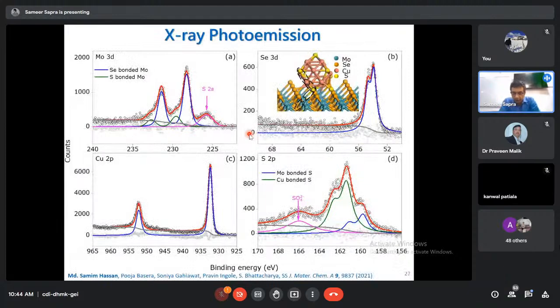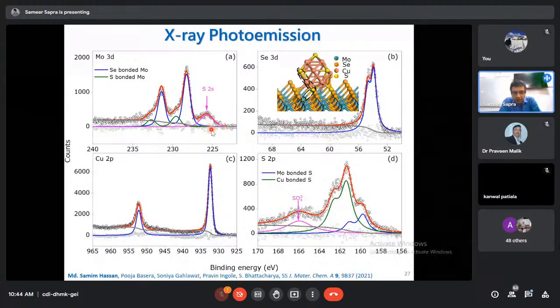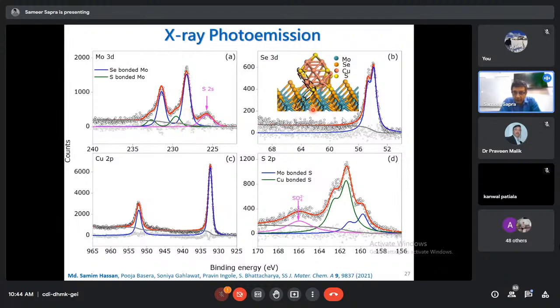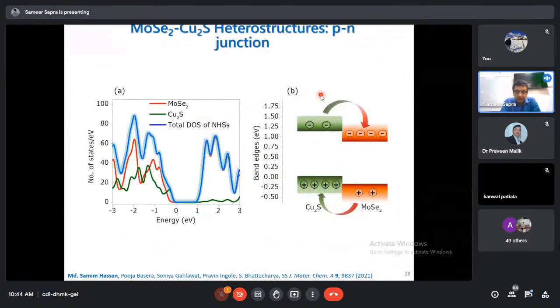But as I was telling you about the model, photoemission data also supports this model that molybdenum is bonded to two different kinds of species. So it's bonded to sulfur and selenium, whereas selenium is bonded only to one species, and that's molybdenum. Copper is bonded only to one species, and that's sulfur, you see on the top. And sulfur is again bonded to two: one is molybdenum and one is copper. And this is what supports, and the intensities also support, the data that this is the kind of model that we should get over here. Okay. Very nice inputs from our DFT collaborators, Shashwata and Pooja.